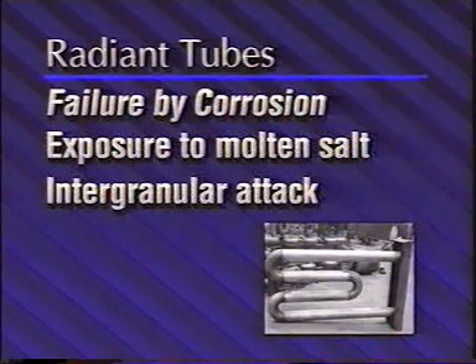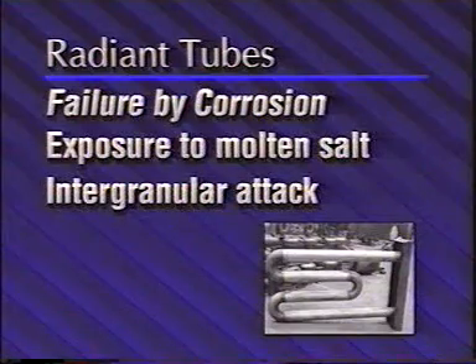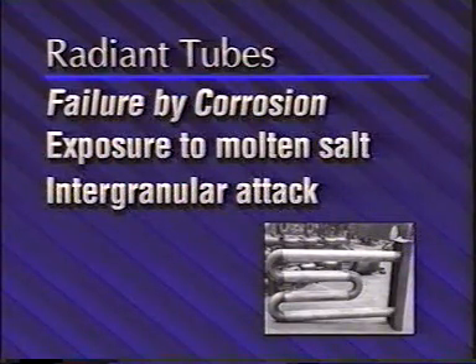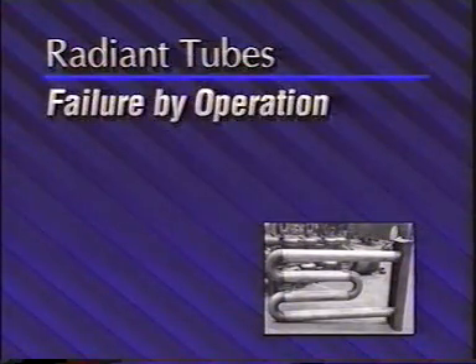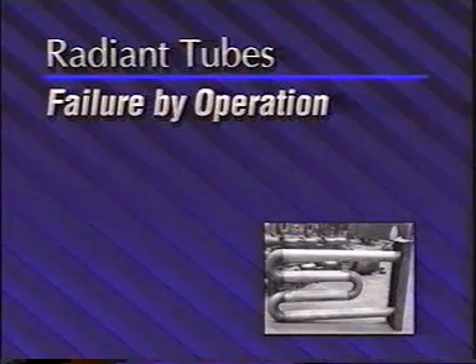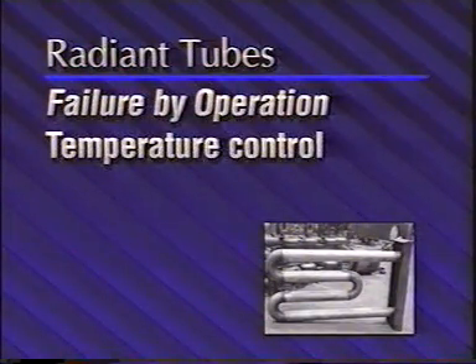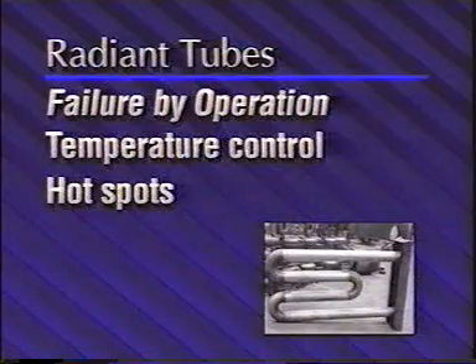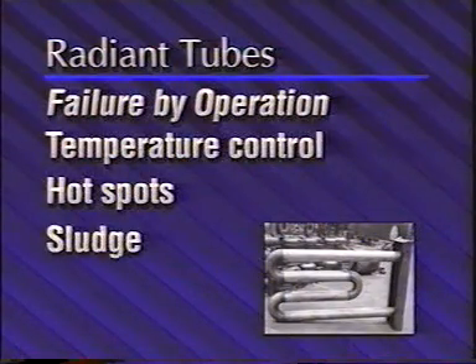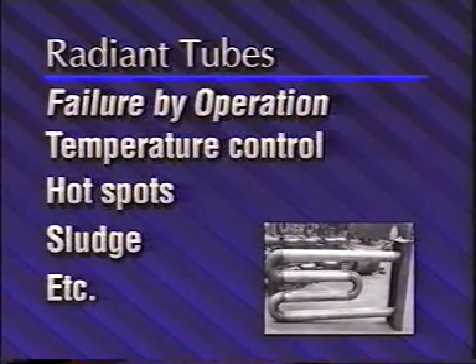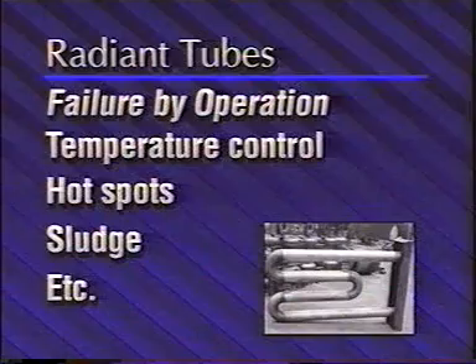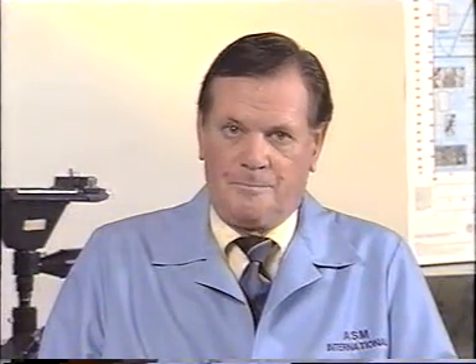Intergranular attack related to chromium depletion at the grain boundaries often contributes to the failure. Failure is sometimes related to variables in the operation of the furnace. For instance, the control of temperature may be lax. Hot spots can exist in the furnace, and sludge can accumulate, all of which may affect the components within the furnaces. The salt pots used in heat treating applications are also subject to erratic service.